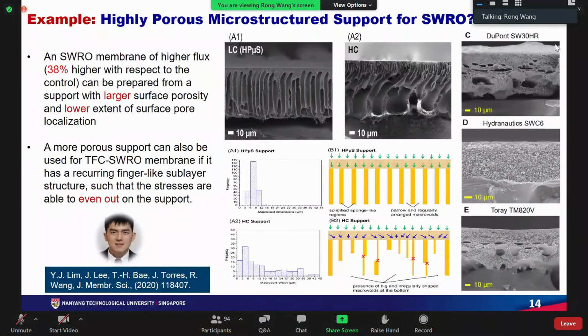Here, I would like to give you an example, and this work was done in my group. We know the operating pressure for SWRO membrane is around 50 to 80 bar, so the mechanical strength of the membrane should be very strong. Commercial SWRO membranes normally have a thick, relatively dense support, as shown in the right-hand side SEM pictures C, D, and E. But we explored the possibility to make a highly porous microstructure support layer for SWRO. We hope to minimize the mass transfer resistance in the substrate and provide a better platform for the IP layer formation. We found a more porous support can also be used for SWRO membrane fabrication if it has a recurring finger-like sublayer structure, so the stress is able to even out on the support.